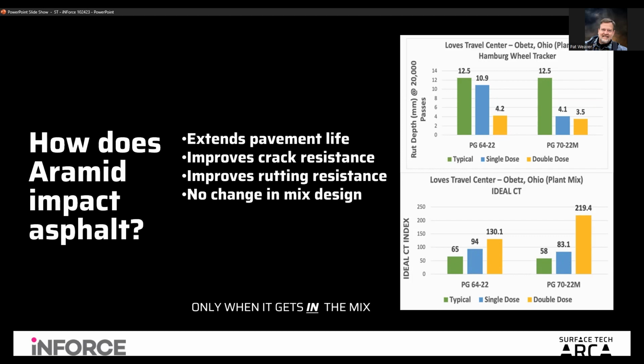Now the 64-22, that's a typical non-modified bitumen in the US. And so the rut resistance on this project with this mix design, and again, I'm not certain what the aggregate nature was, whether it was crushed gravel or if it was crushed granite, not sure. But you can see the double dose really in the neat binder helped tremendously. I mean, it just went from 12.5 millimeters all the way to 4.2. That's a big improvement on rut resistance.